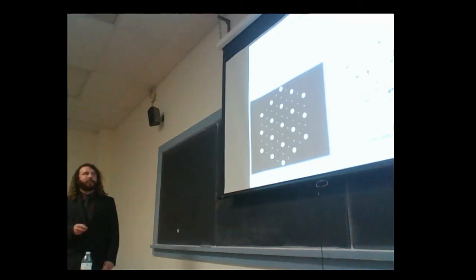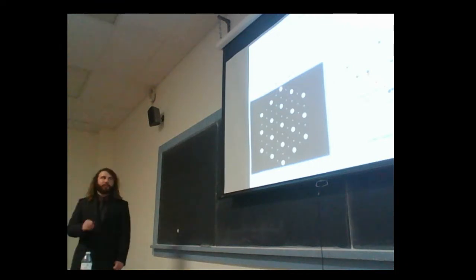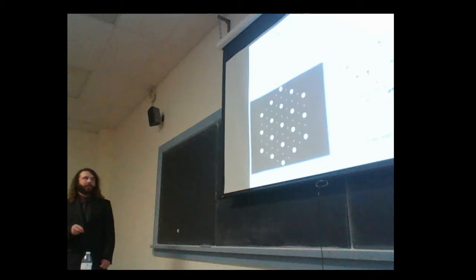This is shown in the phase diagram here, where if we do the same experiment that I showed you with the neutron diffraction scattering, where we find the transition temperature, we find that rather than just the commensurate charge density wave phase here, there's also an incommensurate charge density wave phase that coexists with superconductivity at low temperatures. The incommensuration that I was talking about is like so. This is what a commensurate lattice would look like, and this is what an incommensurate lattice looks like. The difference between these is the incommensuration. And you can see that, again, I would have to go to higher and higher order peaks.